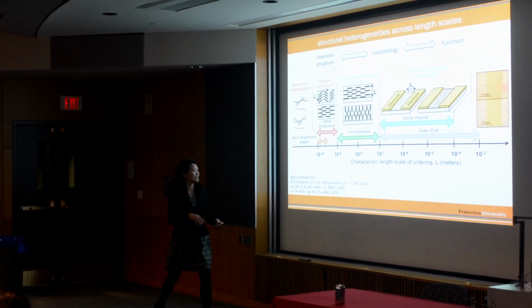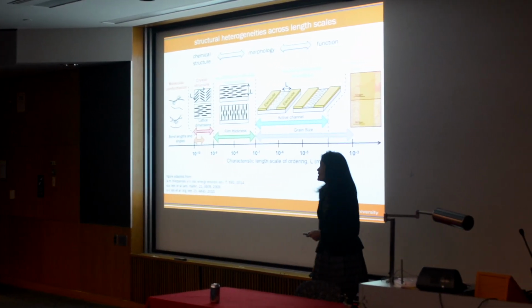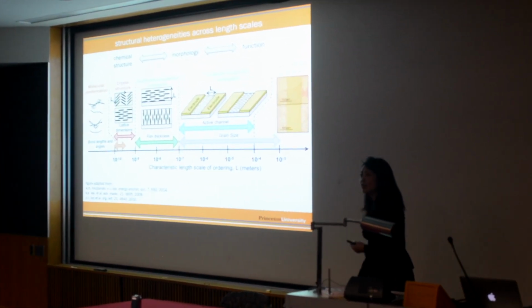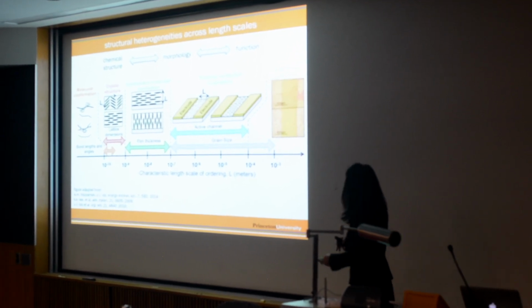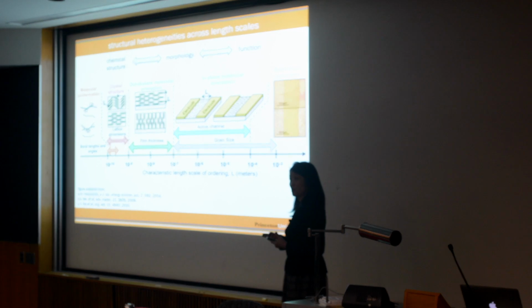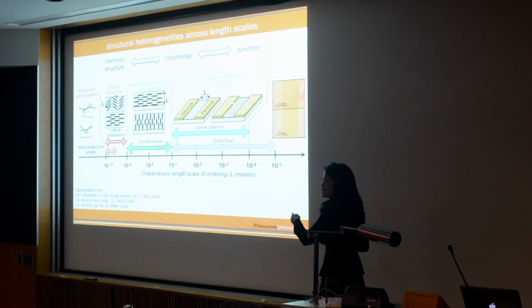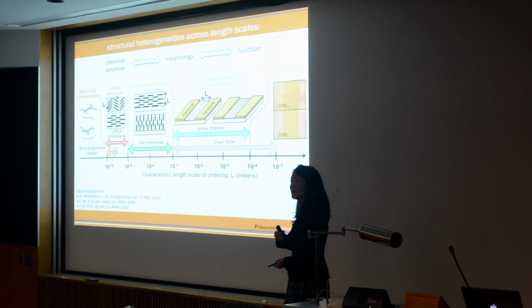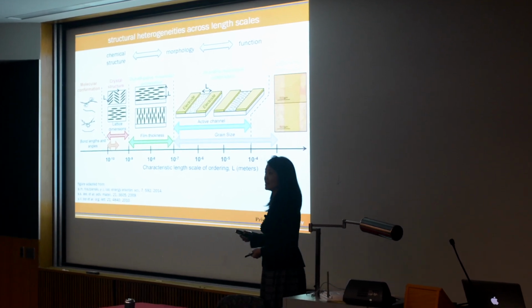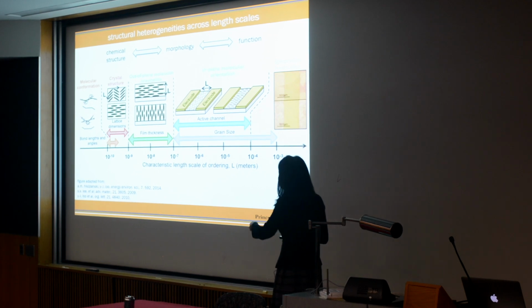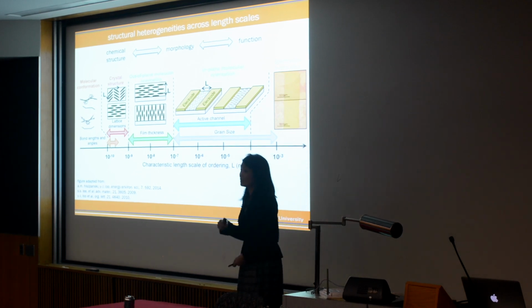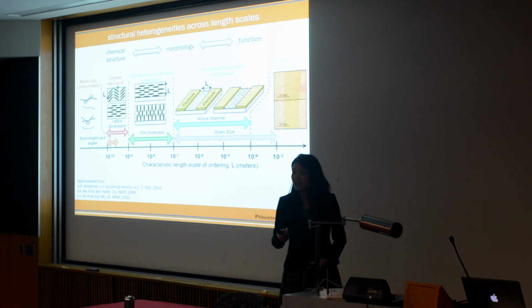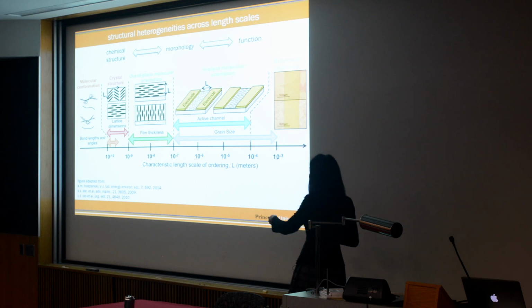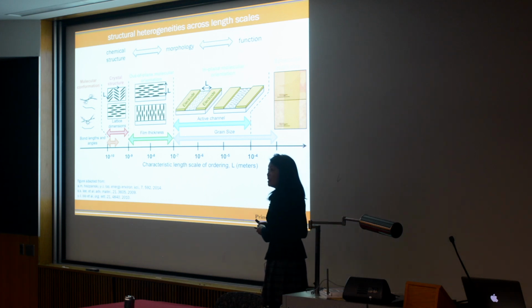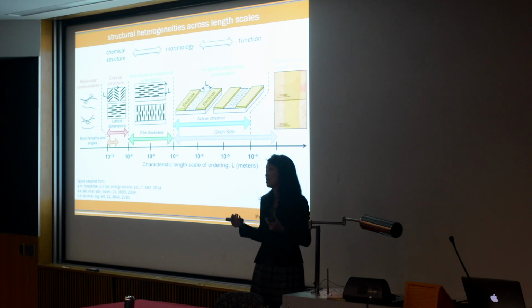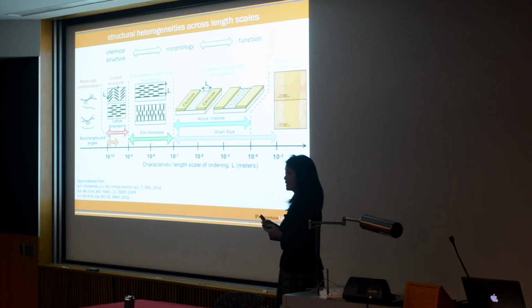And so in the past, let me stand over here, sorry. In the past, we've looked at contributions of grain boundaries. So these are polycrystalline films, so they've got grain boundaries at the largest scale, and how grain boundaries affect charge transport. We've looked at in-plane orientation, because these are thin films, so the molecules can be oriented in plane, and how this in-plane orientation affects charge transport. We've also looked at out-of-plane orientation, because these films are thin, surface energetics matter, and so when you can control the surface energetics, you can get these molecules to either stand up or lie down, and depending on whether they stand up or lie down, that can change the charge transport character of the polycrystalline film.